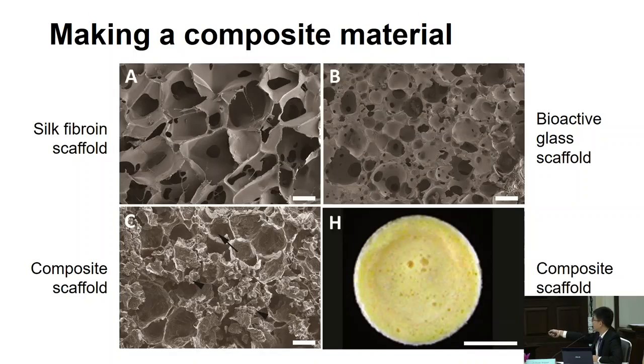This is the composite scaffold that I got. This scaffold is made from silk fibroin together with the bioactive glass. When you look into the microstructure, the bioactive glass scaffold has a structure just like this. They are very porous and have pore interconnection. We can see many pores and interconnected pores. But when we make the composite scaffold, you can see the deposition of silk fibroin protein on the wall of the pores of bioactive glass, and that increases the roughness of the pore wall, and that should increase the bioactivity of the scaffold.